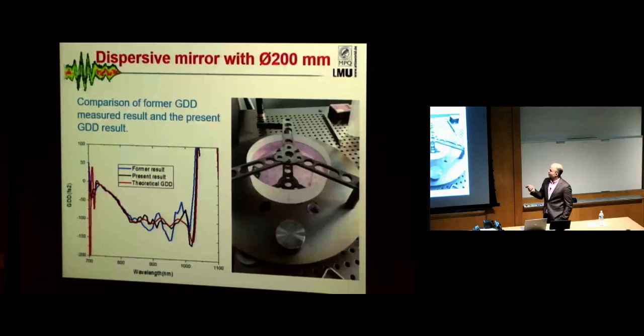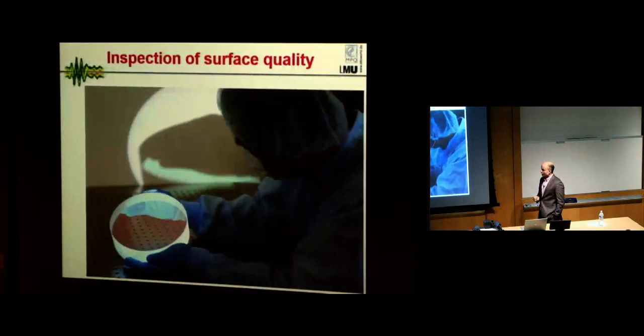These are just examples. This particular mirror was produced on a 200 millimeter substrate. That's how this piece looks. It has a weight of 10 kilograms, and it's mounted to the turntable, which rotates in the chamber. And here again you can see how the original result with which we started looks, and when we optimize our refractive index, we can get much closer to the target. It's just so that you get a feeling that we really need to be very, very close and very precise with our deposition technique.